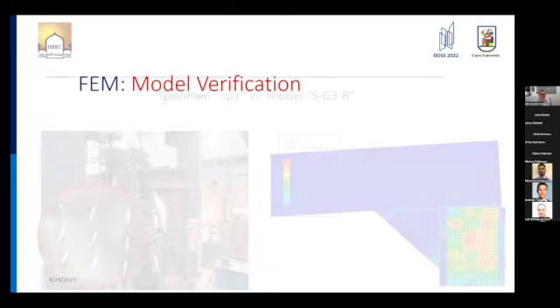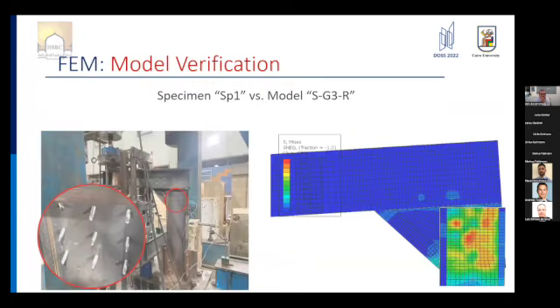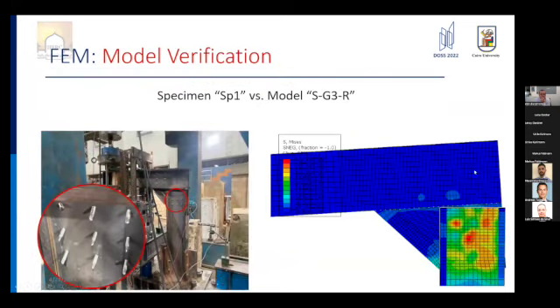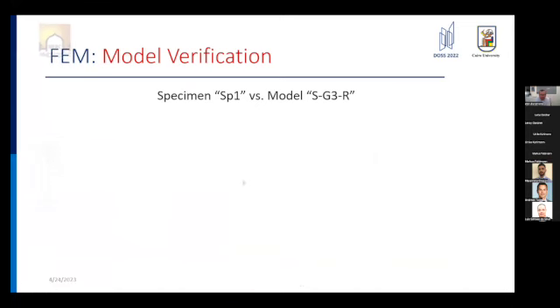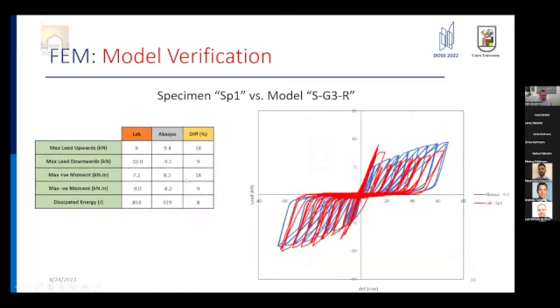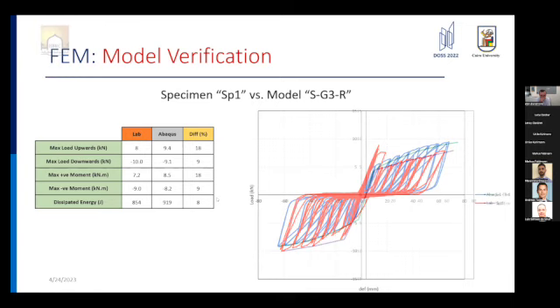The model verification part: we compared the deformed shape of each specimen with its Abaqus counterpart. And we can see here the stress concentration at the location of the screws. This is a comparison between the results. You can see the differences reached 18% when loading the specimen upwards, however only 9% when loading the specimen in the downwards direction. And the difference in energy dissipation was 8%.